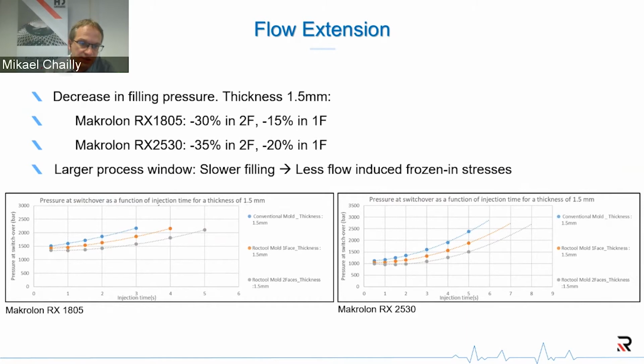We have increasing pressure with the injection time because of the creation of the frozen skin. So ideally, if we take the material on the left, we would need in a conventional molding, now shown in blue, to inject as fast as possible for the optimal time, 0.5 seconds or even less. And as soon as we reach 3 seconds, we cannot inject any longer than that because we would have a short shot.